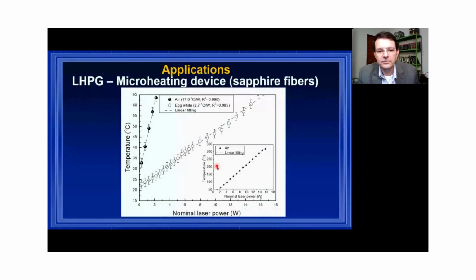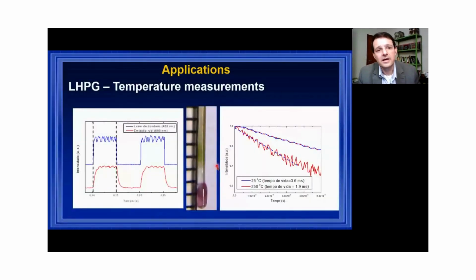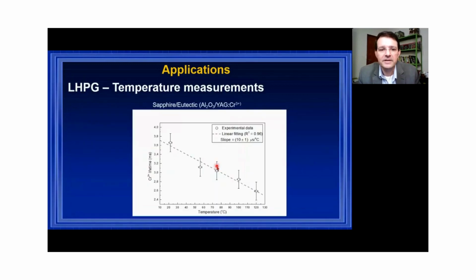Here is the temperature along with the nominal laser power input. You can reach above 60 degrees in egg white. That's interesting. Another application is laser heated pedestal growth with temperature measurements for high temperature measurement, where you put a ruby on a point of the sapphire. Now you measure the lifetime decay of the chromium in this ruby, so you can correlate the lifetime with the temperature. So you can create a thermometer on this, okay?